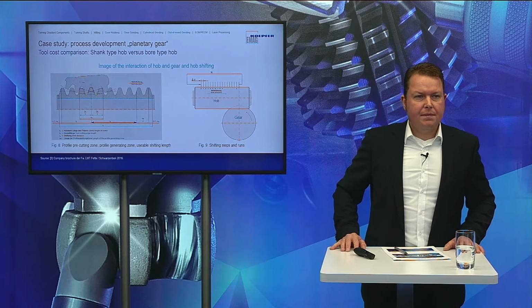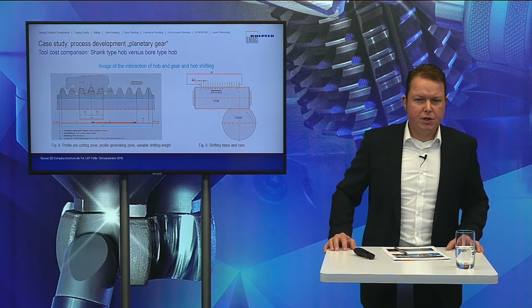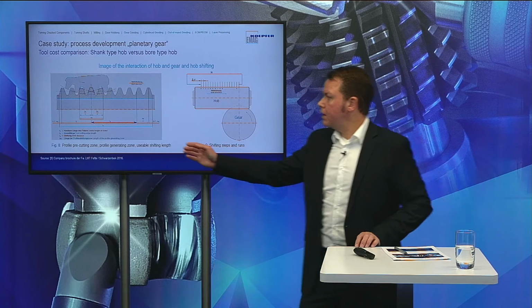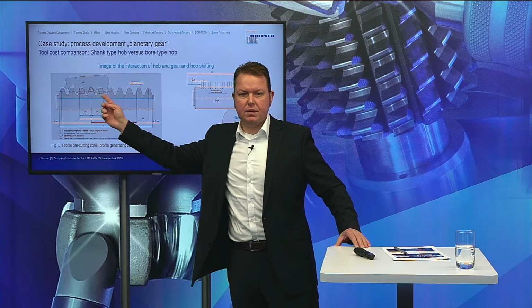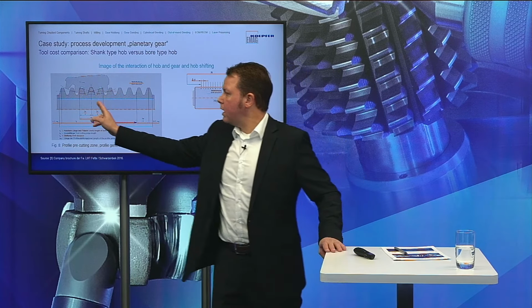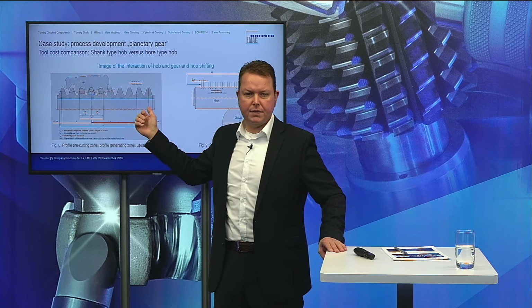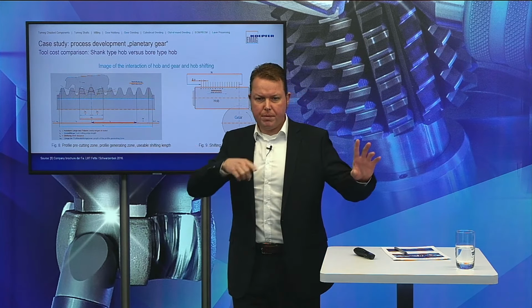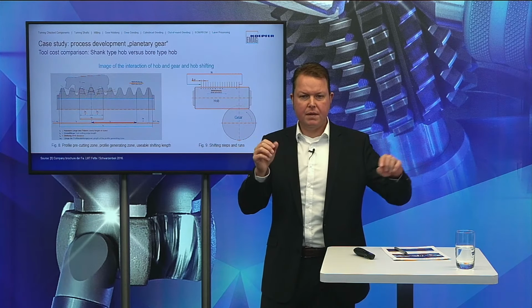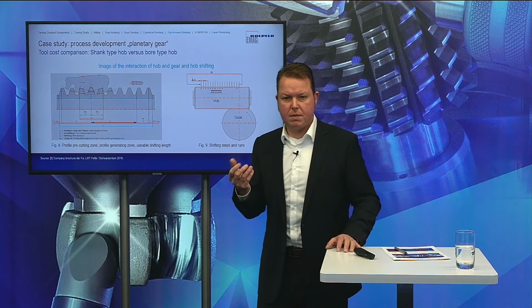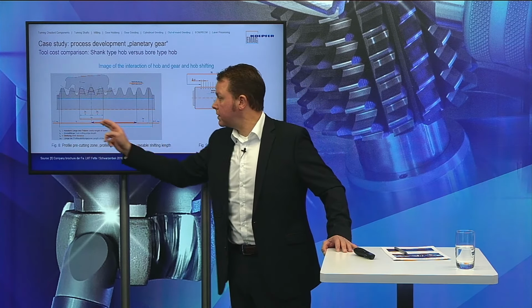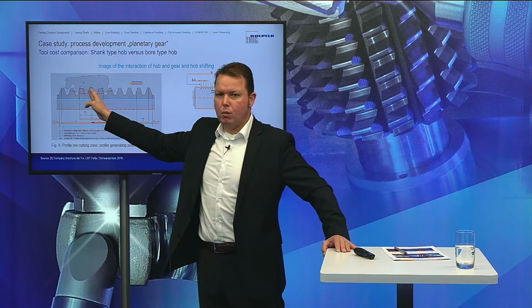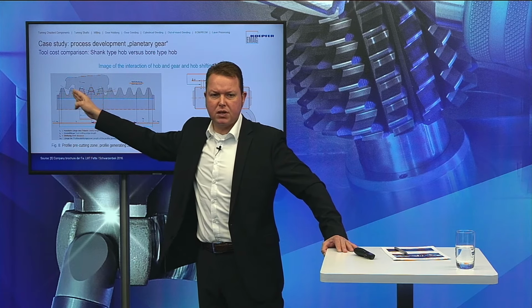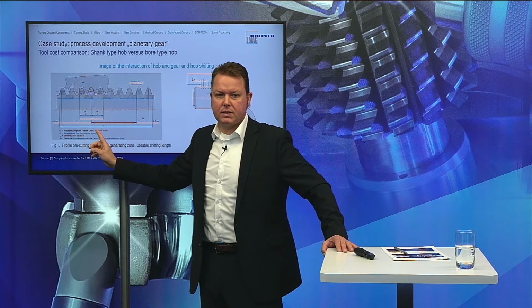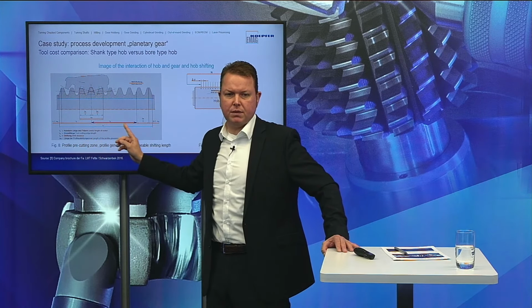Now comes a slide that shows what I mean or why the usable shifting length is so important. We see here the basic rack of the hob, and we see the gear that is being cut, and we have an area on the left side and on the right side that we may not use because the hob is like a spiral. It has teeth at the beginning, at the end, that are not completely built. Thus, we cannot use them and stress them. And this is why we have to neglect this part at the beginning and the end. And moreover, we have on one side the pre-profile, pre-generating zone where we do not create profile. And this leads to the remaining effective shifting length here shown by means of this blue arrow. This is really what we may use on the hob.